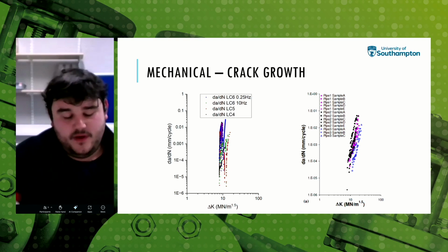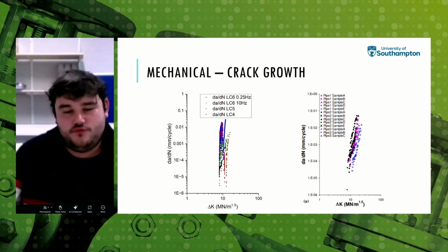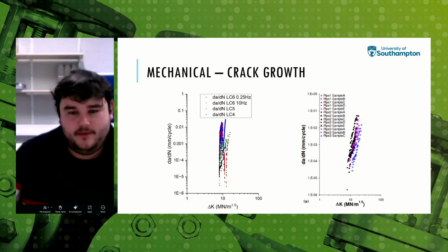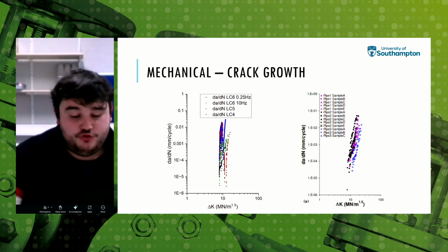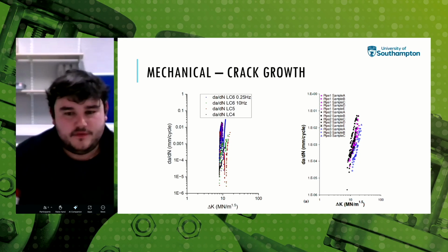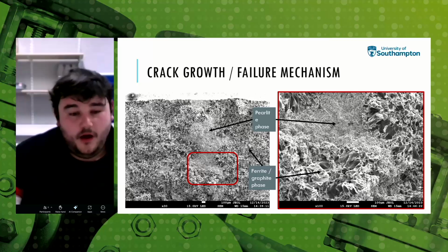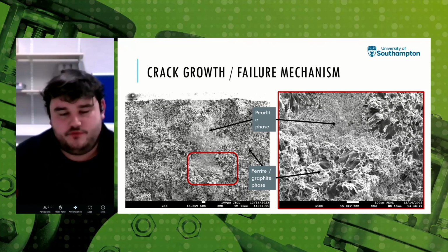So here on the left, we have some data from my testing. On the right, we have some data from literature that other people have carried out in similar materials in a similar manner. As we see, the data is comparable, and crucially, the point to take is there are very small, stable crack growth regions, a very sharp gradient, and effectively, once a crack is initiated, there's very, very few factors in terms of the material and the microstructure that are actually able to arrest the crack and slow its propagation. Once the material is damaged, it tends to just run into failure. So next slide, please. And part of the reason here is because we have these two separate regimes going on.